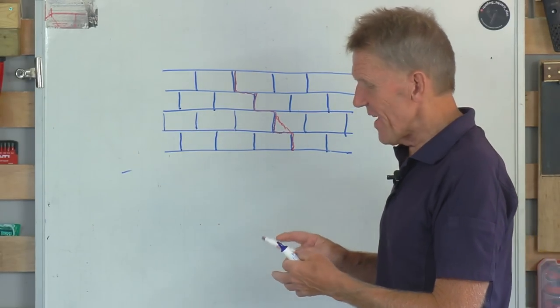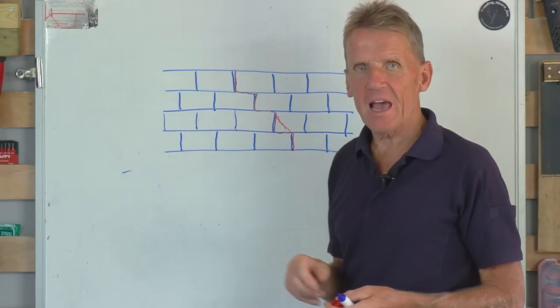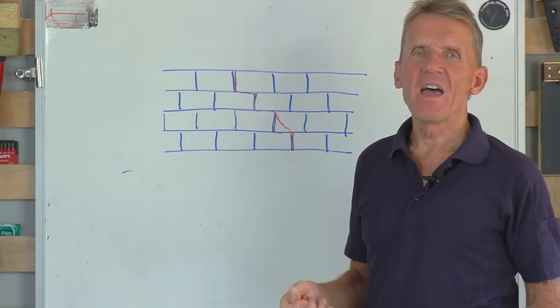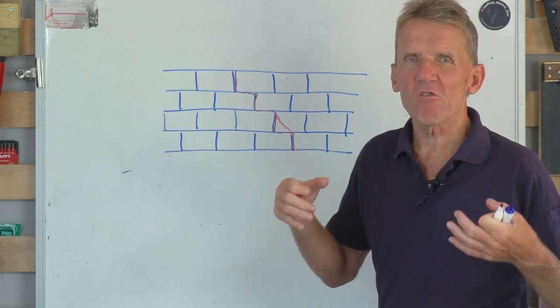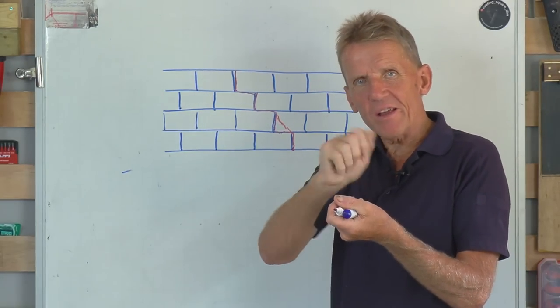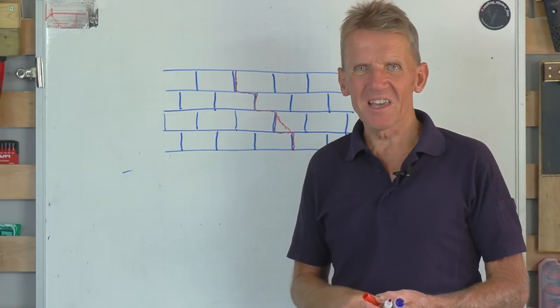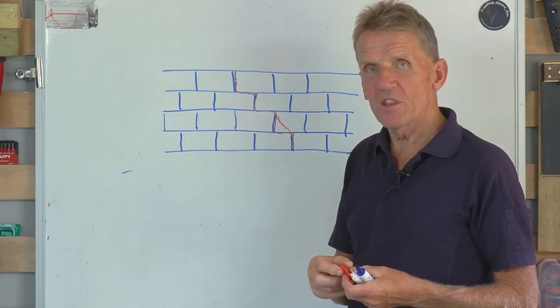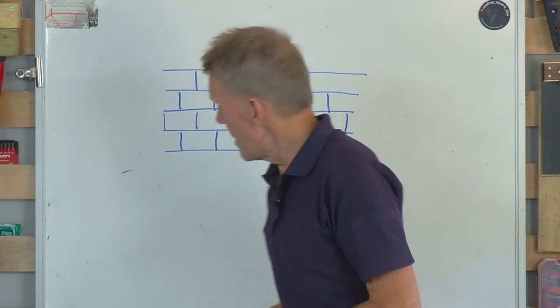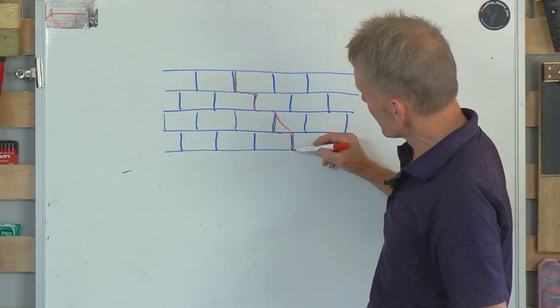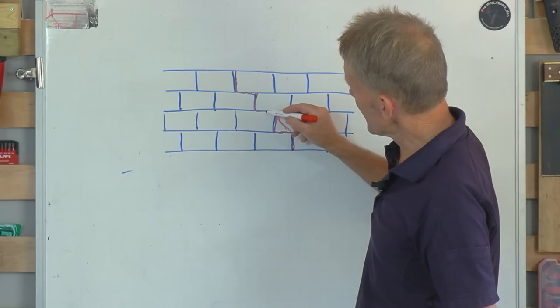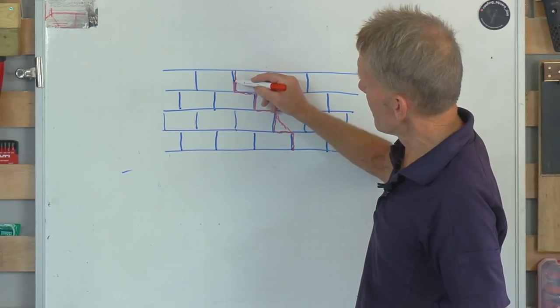But in old buildings that is far less likely to happen because we had what we call sand and lime mortar. That is mortar that didn't have any cement in it. It didn't have any great strength, it didn't have any great adhesion. You could lift these bricks off, you could break the mortar off with a trowel and the bricks were ready to use again. Marvelous stuff. We did away with that because we wanted speed and ease and whatever else and we went for sand and cement.